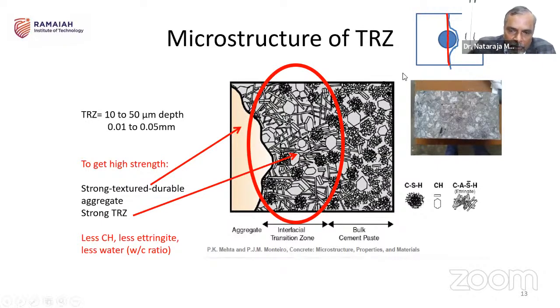So I want to bring whatever the material which is away from the face, that calcium silicate hydrate gel, rather close to the aggregate. For that to happen, I need to see that whatever the calcium hydroxide that is available, which is very, very close to the aggregate phase, eventually reacts with the supplementary cementing material. So many of these supplementary cementing materials, my dear faculty, contain silica, contain alumina. And whatever the calcium you find here abundantly, that eventually reacts with the silica and we get calcium silicate hydrate. It eventually reacts with alumina, you get calcium aluminate hydrate. They are the two strength forming compounds, depending on what type of supplementary cementing materials you are using.